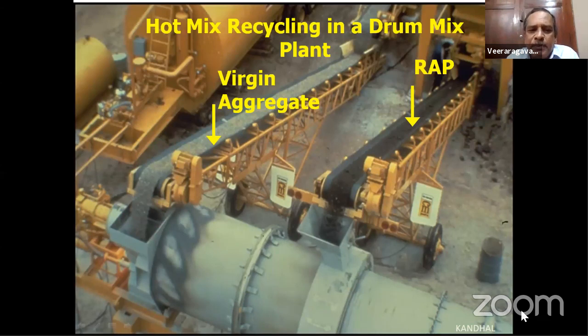What is the issue here? In the case of drum mix plants, here you feed the virgin aggregates, and here you feed the RAP. The virgin aggregates only are heated by the flame. This RAP is already a reclaimed asphalt pavement material, which again has got asphalt. So I would not like to heat this again because it's already hardened. But these virgin aggregates, when I have milled, will lack fines. So these aggregates, when they travel from here to here, get heated. They in turn will heat the RAP.